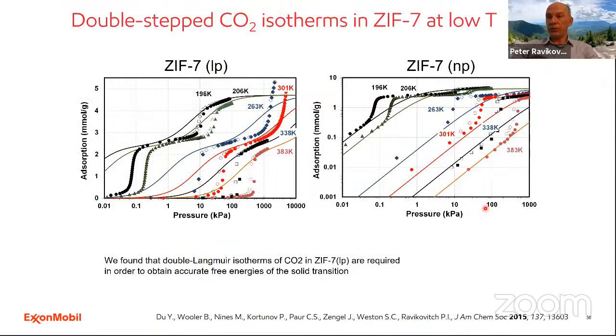Let me go back to ZIF-7. If you look closely at ZIF-7 isotherms, they are actually more complicated. They have two steps. So they have one step, particularly if you measure at low temperature. This is like CO2 at 195K, 200K. It has one step, and then it has a second step, which almost doubles the capacity. And this is the same view in a logarithmic scale.